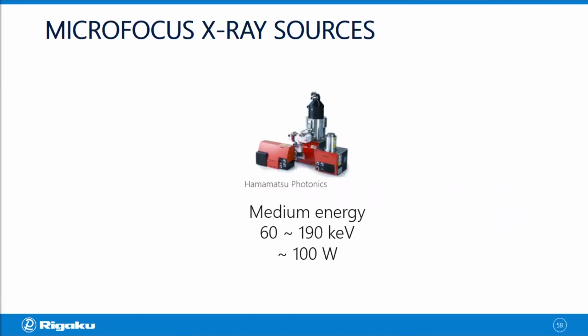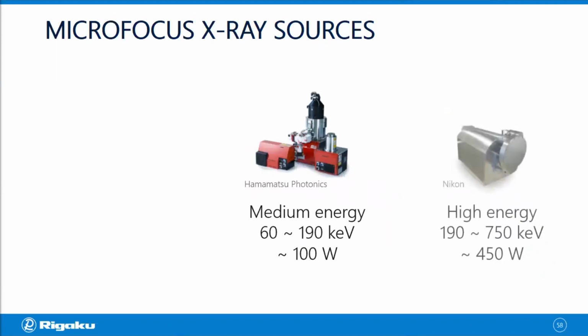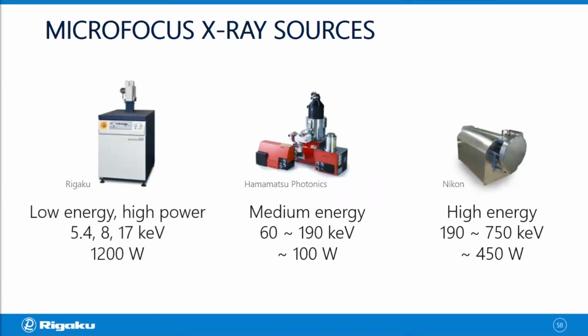But if you want to see something heavy or large, you're going to need higher energy sources. Commonly available ones usually go to 450 kV, but there are X-ray sources that can go up to 750 kV. And their power tends to be higher as well. If you want to see something light or soft and you want to get a high contrast, high resolution image from them, then you're going to have to lower the X-ray energy, but you do not want to lower the power of the X-ray source. In that case, you need a different type of X-ray source like this one.